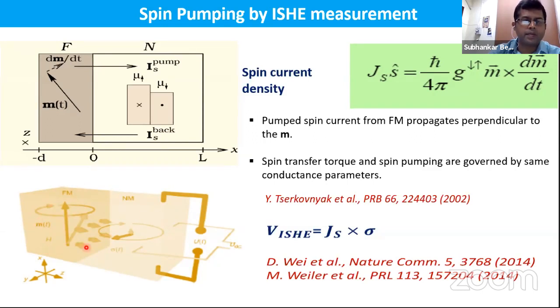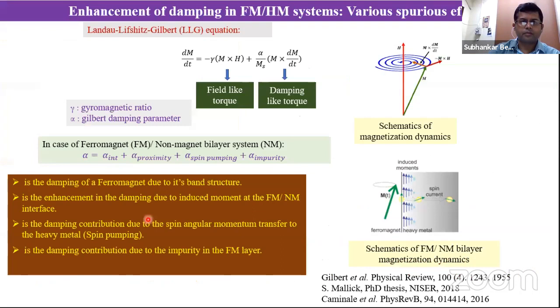So this is like a spin source, and this is like a spin sink, and then you detect it, and that's basically the whole idea of spin pumping, because spins are getting pumped. And by that, if you measure the damping of the single layer and the damping of the bilayer with this heavy metal or any other material, you will see that damping gets enhanced for the bilayer system, just because there is spin pumping. So I think this slide I can skip.